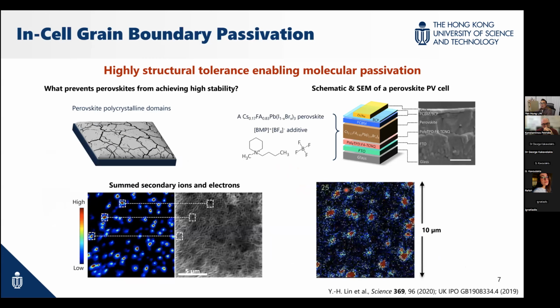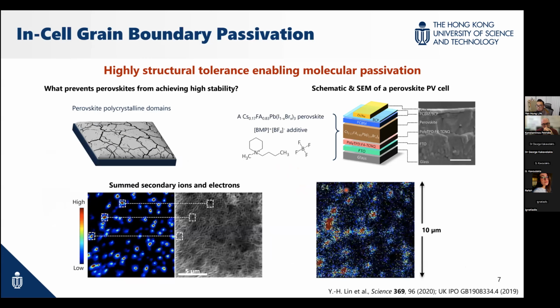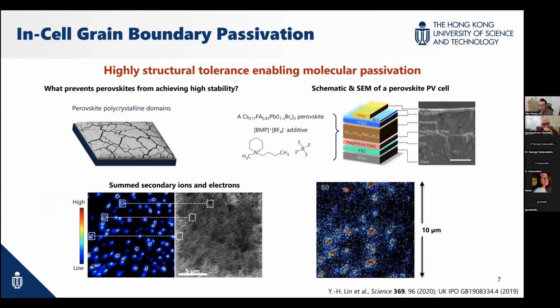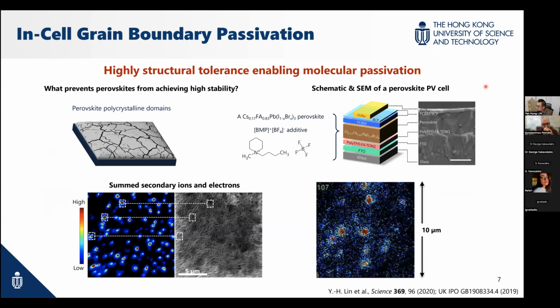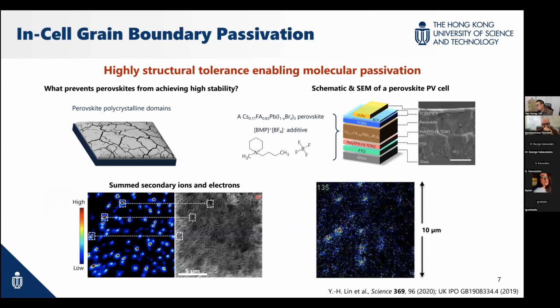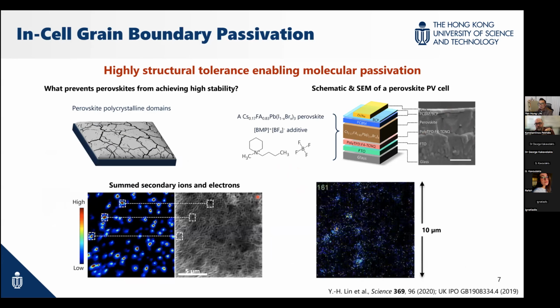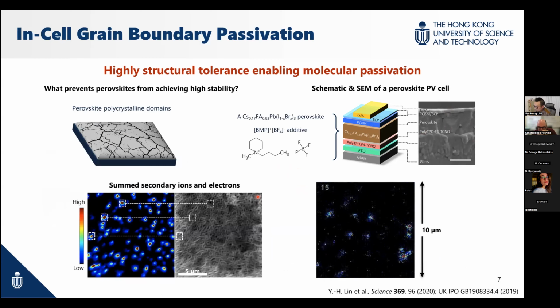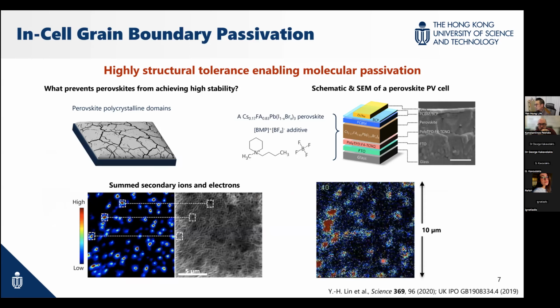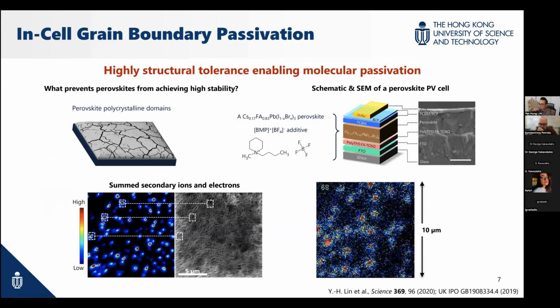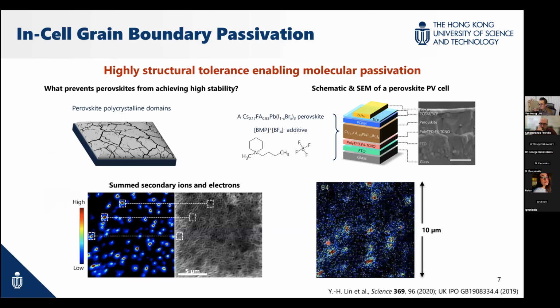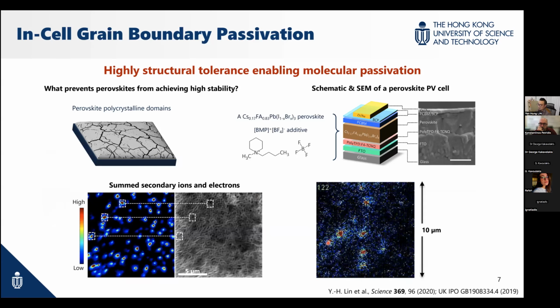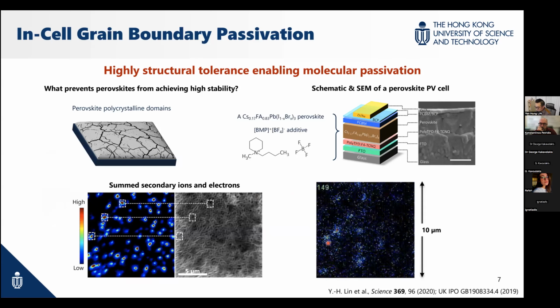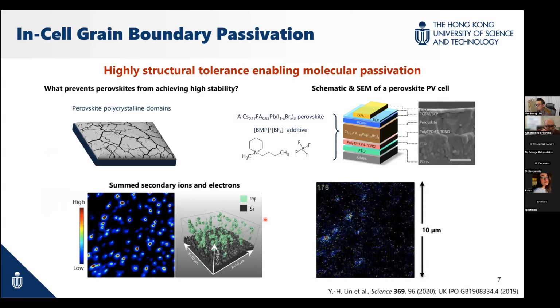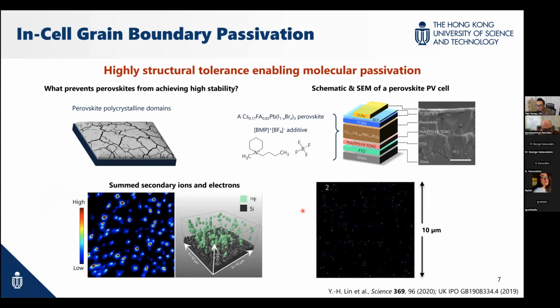So we simply blend this additive into the perovskite precursor. We deposit films and form this kind of polycrystalline film. And we try to identify exactly the whereabouts of this ionic additive. So we use ToF-SIMS. The animation you see here is where we take out the film layer by layer, at higher resolution. So we are able to construct the distribution of these organic molecules.